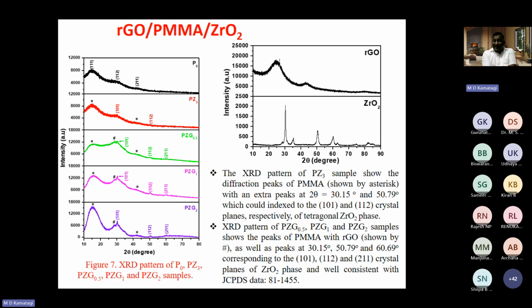The XRD pattern of the polymer and ZrO2 nanoparticle sample shows diffraction peaks corresponding to PMMA as well as that of ZrO2. The XRD pattern of the composites, polymer, metal oxide nanoparticle and graphene oxide, at different weight percent, 0.5, 1 and 2%, shows the peaks corresponding to all. That means we have successfully incorporated both ZrO2 and graphene oxide into the PMMA. And they are well consistent with the reports.